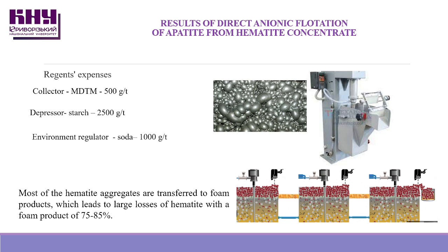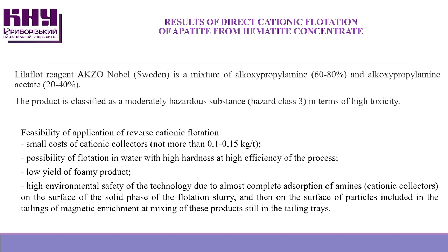During direct anionic flotation, most of the hematite aggregates pass into the foam product, which leads to large losses of hematite with the foam product, 75 to 85%. So further studies were conducted on the direct cationic flotation of apatite. The Lilaflot reagent was used for direct cationic flotation of apatite. Lilaflot reagent is a mixture consisting of 60 to 80% alkoxypropylamine and 20 to 40% alkoxypropylamine acetate.